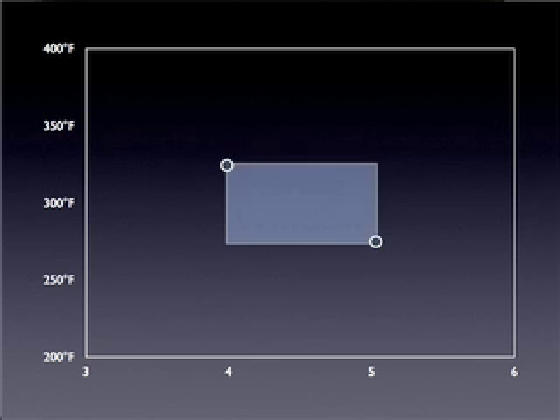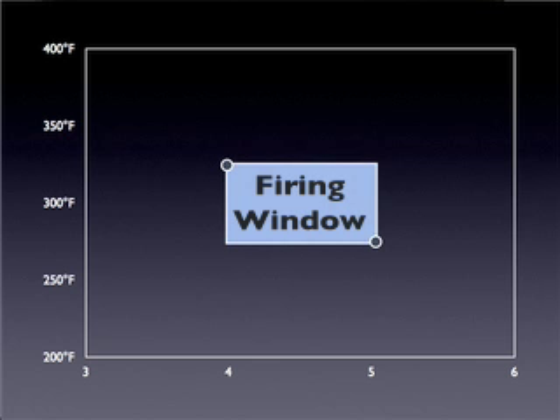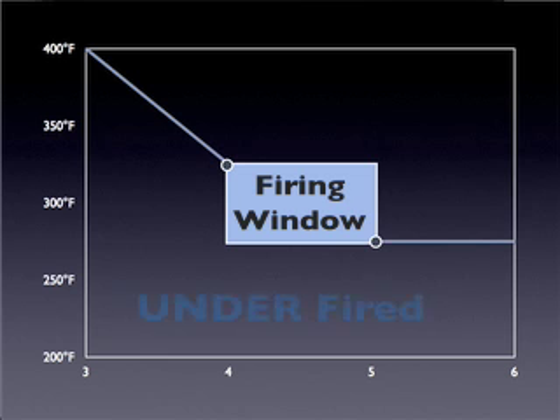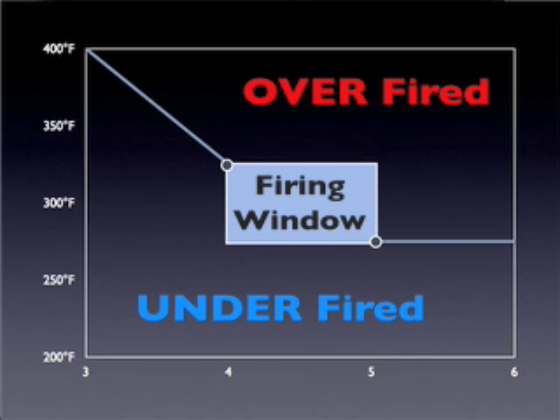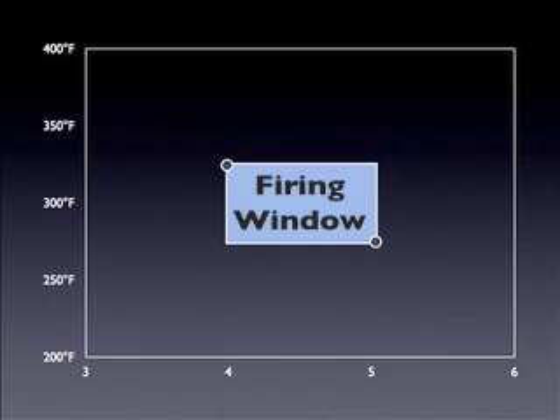If we go outside this firing window of time and temperature, we can find that if we put the turkey in for less than the desired maturing, the turkey is somewhat under-fired. If, on the other hand, we leave it in for excess of the maturing temperature and time, the turkey will come out over-fired. So what we're after is a certain amount of time and temperature to mature the turkey so that we obtain a high-quality product. We then have what is commonly referred to in maturing this product as a firing window.